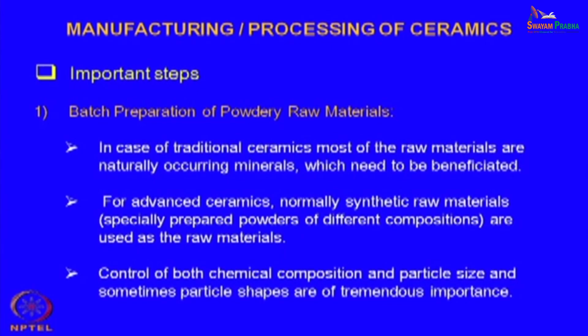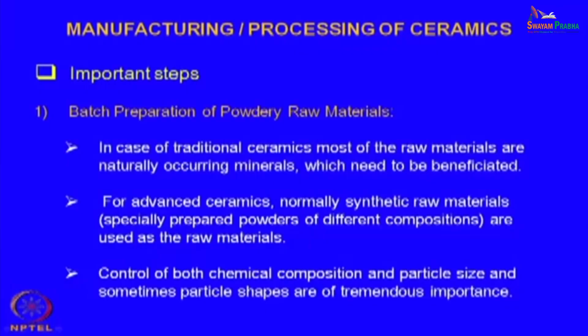Control of both composition and particle size, and sometimes particle shape, is of tremendous importance. As I mentioned, the chemical composition is important, and particle size is important, so that with finer particles your starting material has fewer pores or open spaces between the particles, so that consolidation and mechanical strength development become easier at a later stage. Then you have different shapes of the particle, sometimes spherical, sometimes more angular, sometimes little cuboid shapes. Depending on the crystal structure you can get hexagonal crystals. So, shapes are also important depending on the particular nature of the raw material and the product you want to make.